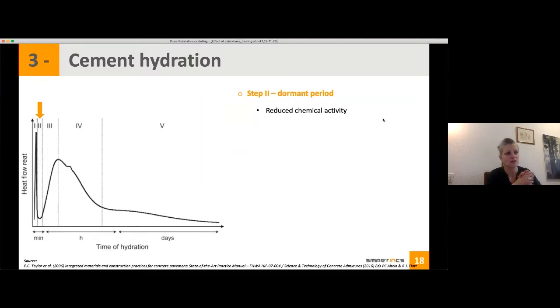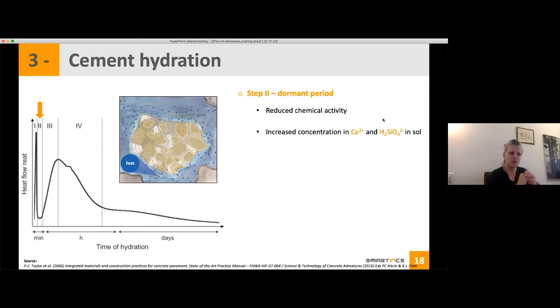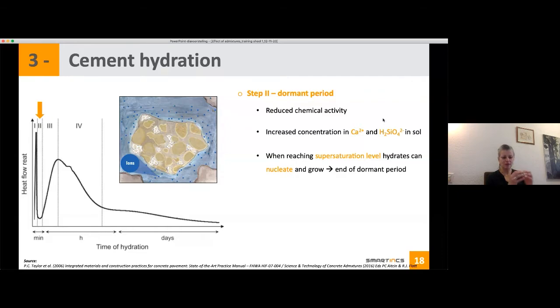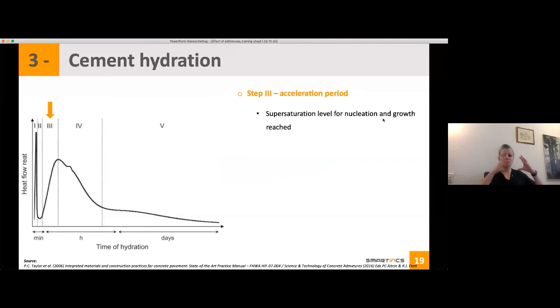And this is what you see in step 2. It's called the dormant period. And this period is characterized by reduced chemical activity. So what happens during this period? You will still have a dissolution of your silicate, but this comes very slowly, and then you will accumulate in your solution some calcium ions and some silicate ions. And when the concentration of these ions reaches a certain value, a supersaturation level, then you have enough to nucleate, and then they will grow. And when they grow, then the chemical reaction will speed up again.